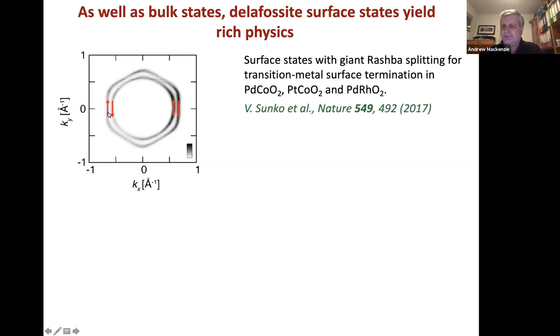And after a referee queried the model, we grew palladium rhodate, where rhodium has a far bigger bare scale because it's a 4d metal, and studied the surface state Rashba split in that. And it completely conforms to that expectation. You get about a 150 millielectronvolt Rashba split for palladium rhodate and a 70 millielectronvolt one for palladium cobaltate. So there's no magic here, but it's telling you that the way you've intuited this physics wasn't completely correct, and that there are special structures that give you a much bigger effect than you expected to see. I see. Thank you.